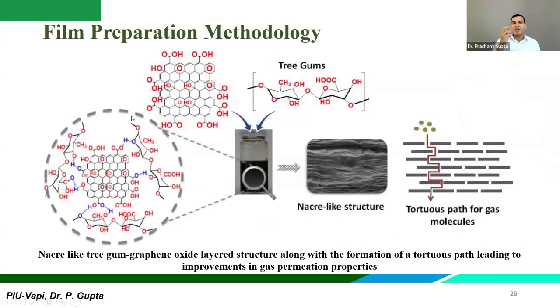This is an example where we are talking about a tree gum. The gum that we eat in winters to keep our body warm, right? So tree gum combines with graphene oxide, which is a nanomaterial. This tree gum is mixed with graphene oxide material, which is black, and you get a nacre-like structure, a pearl kind of structure. Because of this, the material's air permeability is very poor. And because of these graphene oxide nanoparticles, it has created a path where the gas has to navigate itself. So it decreases the rate of gas permeation.